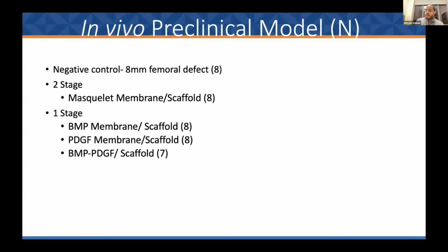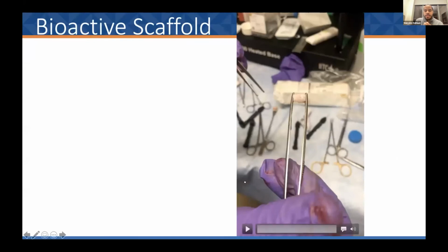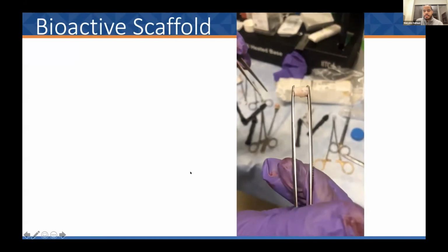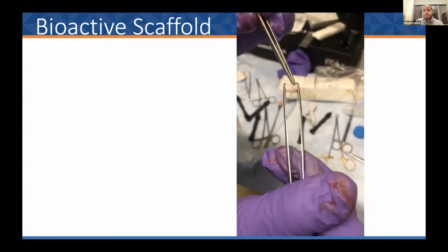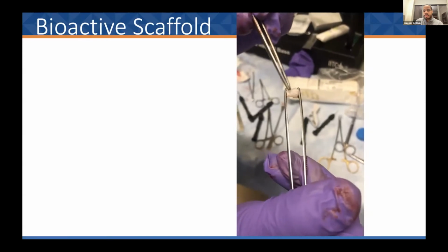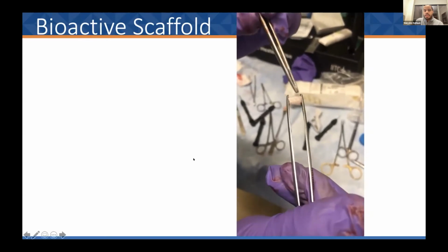And then we also had our experimental groups, which had different types of growth factor incorporated into the synthetic membrane, and we implanted that in a single stage procedure at the time of the critical defect creation. So I'll just show this video real quick. It's important to note that all aspects of the scaffold are covered in this membrane. So that's the membrane. It has some nice usability properties to it, and the scaffold underneath was created specifically for an 8 millimeter defect.